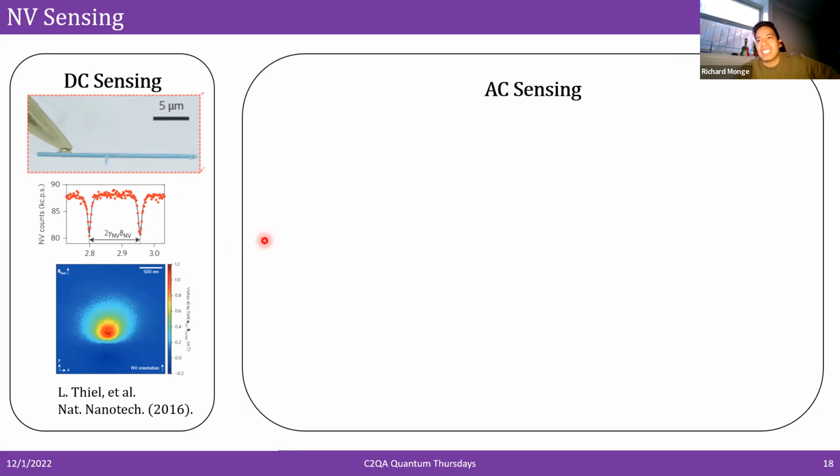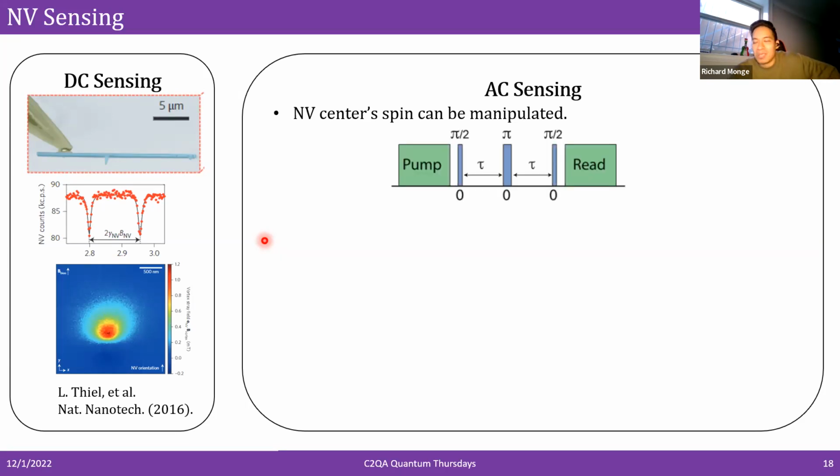One of the advantages, like I mentioned before, of the NV center is the ability to implement time-resolved protocols via a series of microwave pulses, like the Rabi oscillations that I showed you. So we can implement a pulse like this. One can engineer a pulse to filter out specific frequencies and obtain information about the source of noise that's responsible for the NV spin lifetime or decoherence.